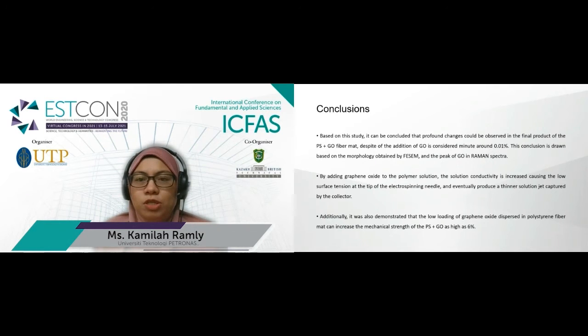around 0.01%. This conclusion is drawn based on the morphology obtained by FESEM and the peak of GO in the Raman spectra. By adding GO to the polymer solution, the solution conductivity is increased, causing low surface tension at the tip of the electrospinning needle and eventually producing a thinner solution jet captured by the collector. Additionally, it was also demonstrated that the loading of graphene oxide dispersed in polystyrene fiber mat can increase the mechanical strength of the PS-GO by as high as 6%.